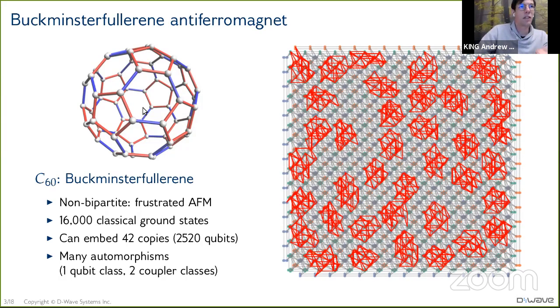So you have huge degeneracy if you just look at the antiferromagnetic case where everything is +1. You get 16,000 classical ground states. And in this Pegasus graph, you can actually embed 42 vertex disjoint copies using over 2,500 qubits. You'll note that even though this seems like a sparse smattering of buckyballs, this is using more qubits than you had available in any of the previous processors. Back to the automorphisms, you'll notice that each spin is incident to 2 red couplers and 1 blue coupler here. This graph is actually vertex transitive, meaning that there's an automorphism mapping any spin to any other spin. If you take a soccer ball and you hold it such that some 5 cycle is oriented in some orientation facing you, you can do the same thing for any 5 cycle in any orientation. This allows us to study statistics of things that should be degenerate and sometimes are not.